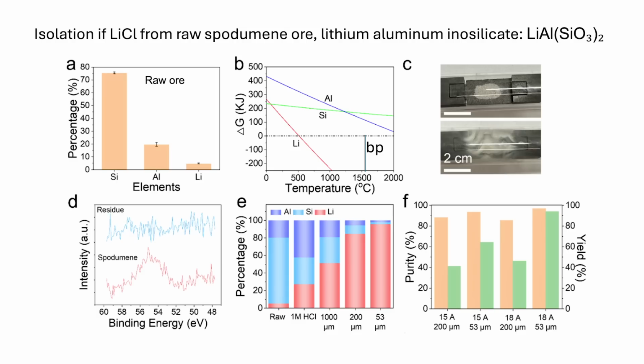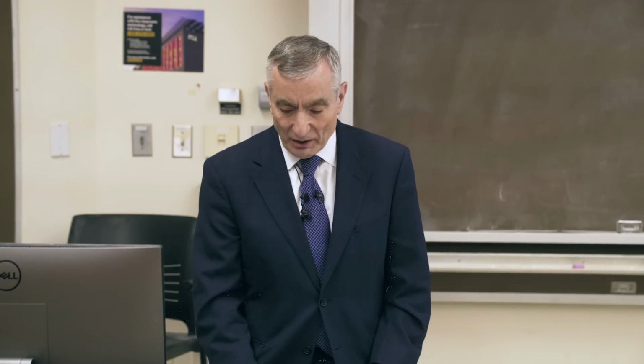So what you can do is you can just look at the thermodynamics. Aluminum and silicon should not chlorinate. You should form lithium chloride right here at about 520 degrees. Lithium chloride should form when you flash under chlorine. Lithium chloride distills out at about just over 1500 degrees. So just heat your reactor, flash your reactor to about 1550. You should get lithium chloride, and it distills right out. And indeed it does. So we can distill out lithium chloride. We can get a purity of about 95%. We can get a yield of about 95%, 92%, something like that, directly out of a mineral that is all over the United States. We have access now to lithium in large quantities.